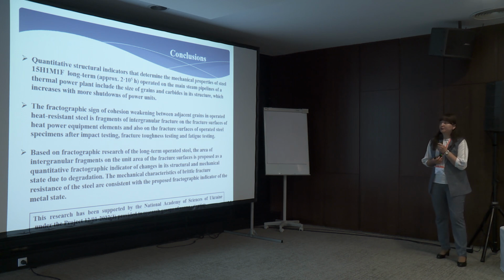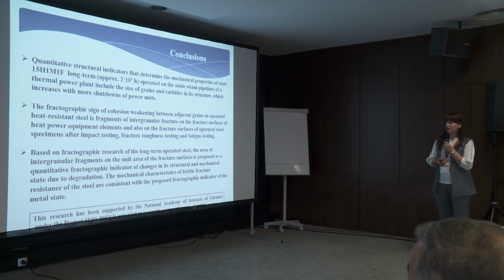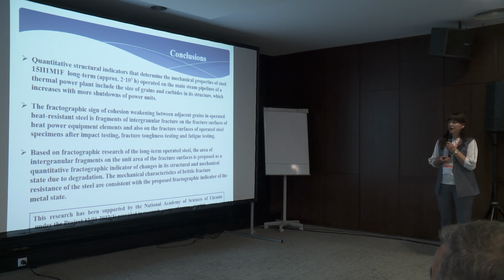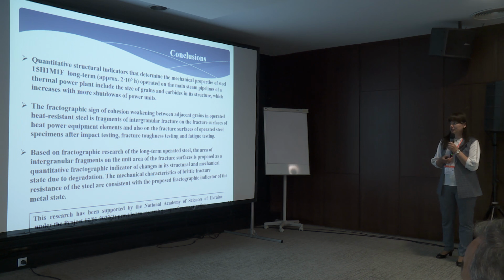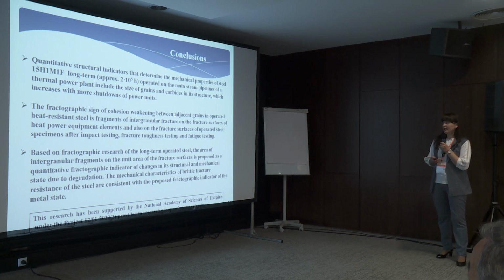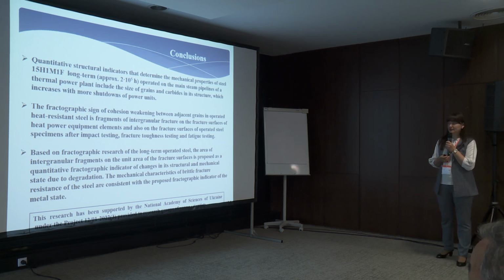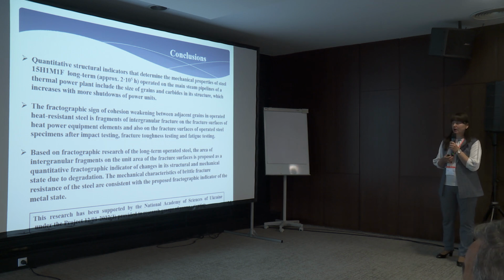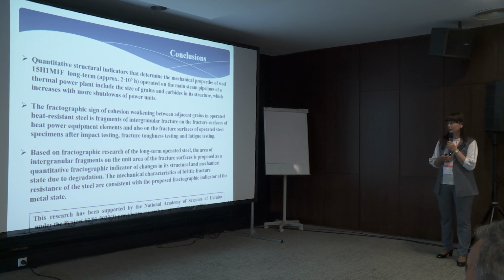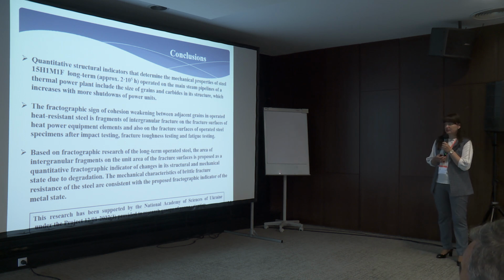This concludes our presentation. Quantitative structural indicators that determine the mechanical properties of heat-resistant steel long-term operated on the main steam pipeline of the thermal power plant include the size of grains and carbides in its structure, which increases with more shutdowns of power units. The fractographic signs of cohesion weakening between the adjacent grains in operated heat-resistant steel are fragments of intergranular fracture on the fracture surface of the heat power equipment element, and also on the fracture surface of operated steel specimens after impact testing, fracture toughness testing, and fatigue testing.